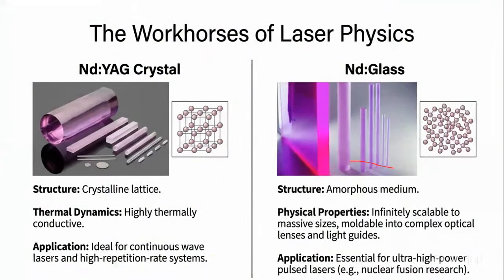Now coming to the basic material, here you have Nd:YAG crystal as well as Nd glass laser. In the Nd:YAG crystal, what you see is the lattice. It has a crystalline structure with long range ordering, and thermally it is highly conductive. Whereas here it is not a long range ordering network. It is a random network, which we call an amorphous medium, and it can ensure that the material doesn't undergo any significant thermal agitation. And again, what you see here is the application for continuous wave laser, whereas here you see it for pulsed beam laser.